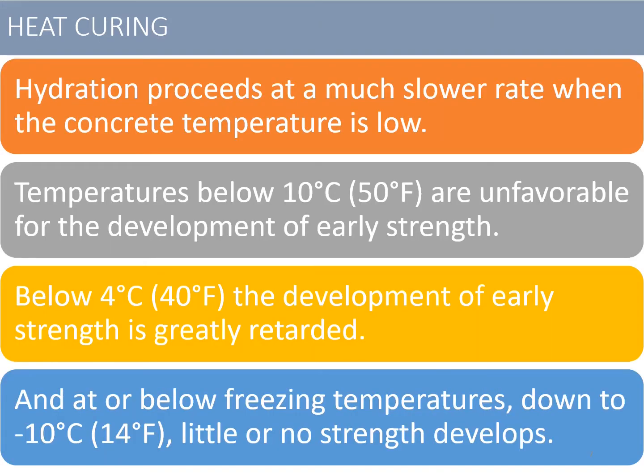So hydration proceeds at a much slower rate when the concrete temperature is low. Temperatures below 10 degrees are unfavorable for the development of the early strength, and below 4 degrees the development of the early strength is greatly retarded, and at or below the freezing temperatures, maybe down to minus 10 degrees centigrade, little or no strength development is observed in the concrete. So these are the conditions where you should look for the heat curing.